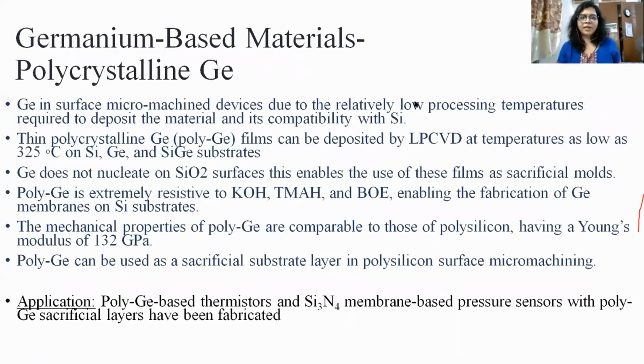Now coming to germanium-based materials. Germanium-based material like silicon germanium has been used long back for early transistors and strain gauges. It is extensively used in surface micromachining due to its low process temperature, and it is also compatible with silicon. Polycrystalline germanium thin film can be deposited by low pressure CVD at a temperature lower than 325 degrees Celsius on silicon and silicon germanium substrates. Germanium does not nucleate on silicon oxide, enabling it to be used as a sacrificial mold. The residual stress in germanium can be relaxed completely when annealed at 600 degrees for 30 seconds. Polygermanium is highly resistant to etching by KOH, which enables us to fabricate polygermanium membranes.